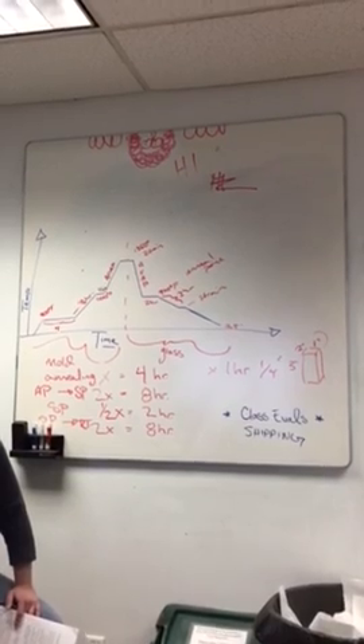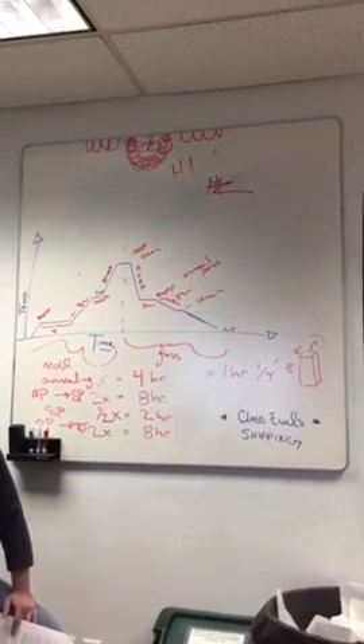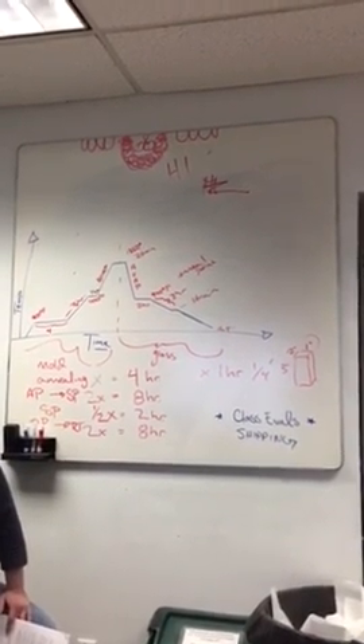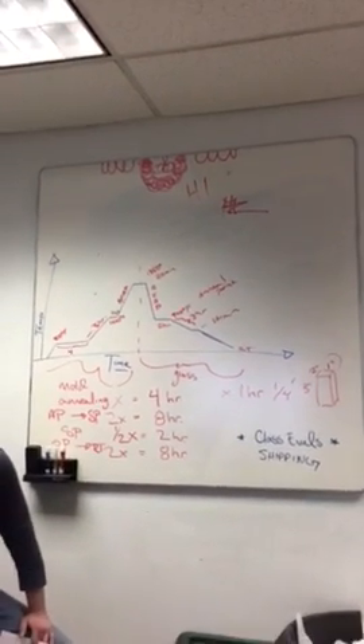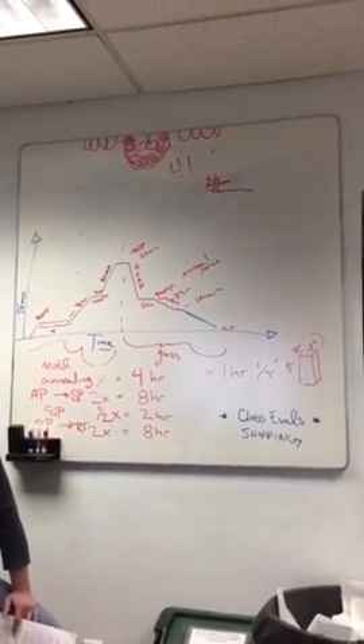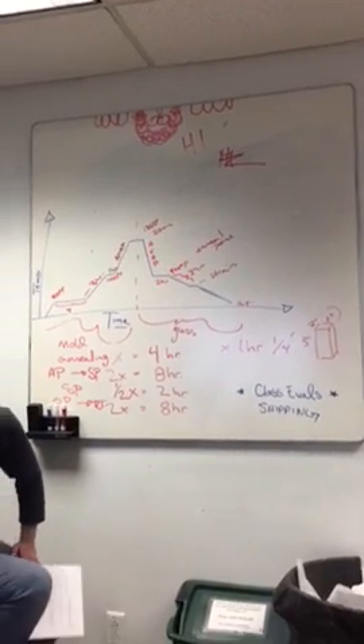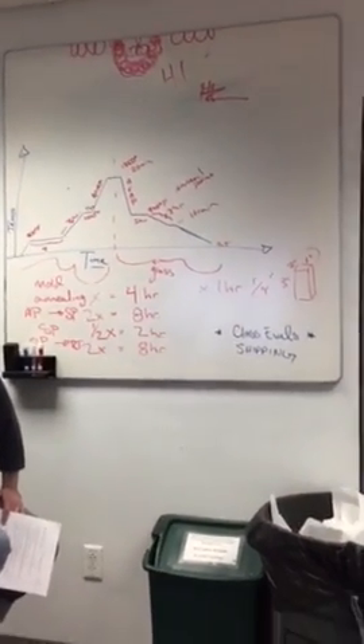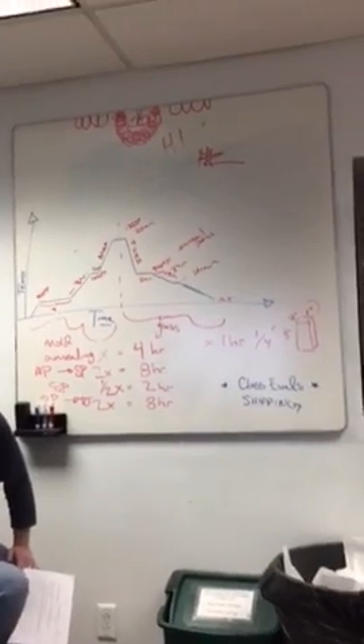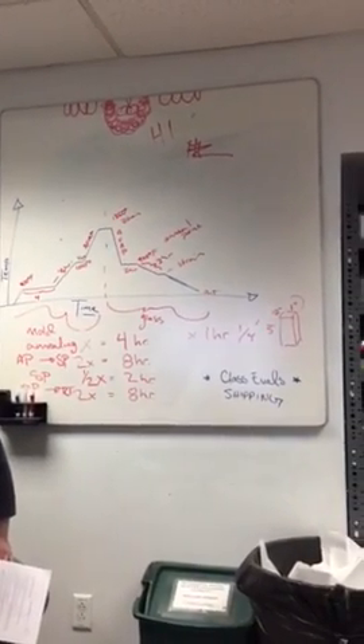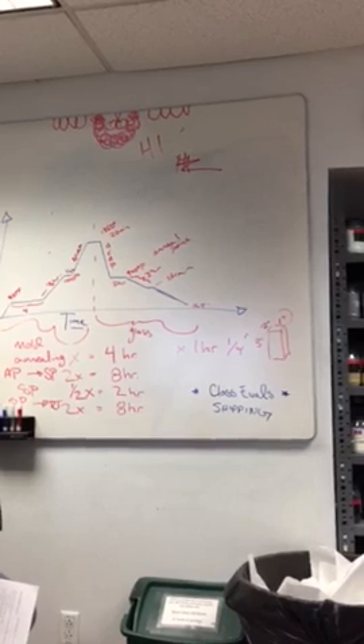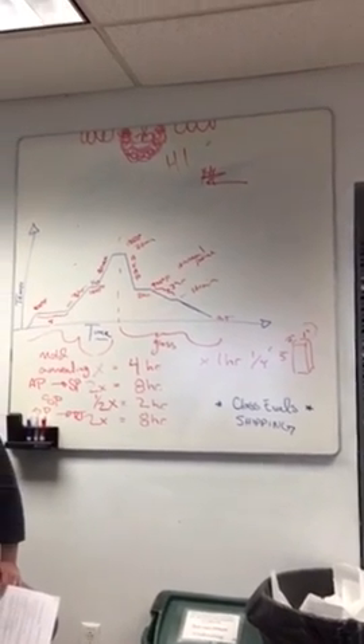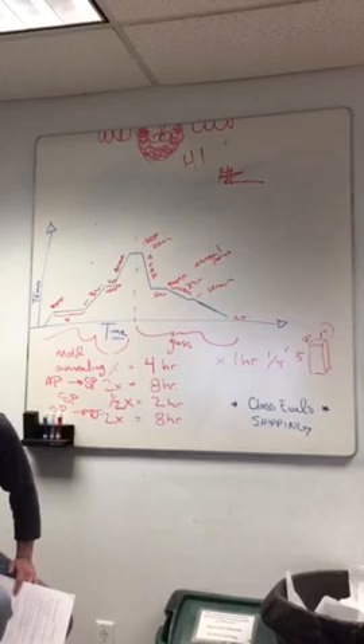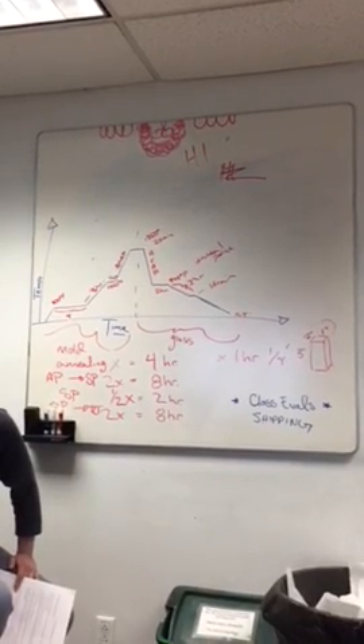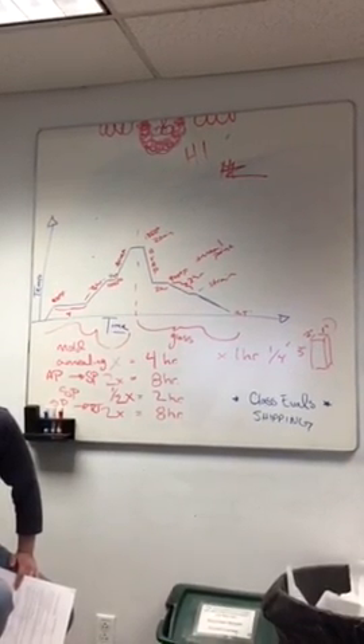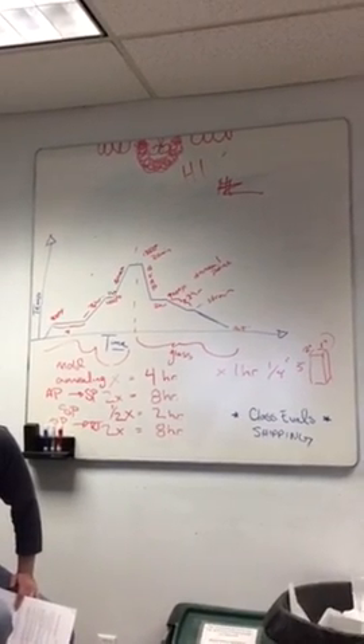I have not found devitrification to be a problem if it is a completely enclosed, three-dimensional lost wax casting. If it is something that, in pâte de verre, again, it's not an issue for us. If it's something that is a wide open, flat casting with lots of surface area that's exposed in the kiln, that is where you could run the risk of forming devitrification, and that would be one instance where I would consider coming in to crash the kiln, to move from process temperature down to annealing point. For this specific application, you do not need to do that.